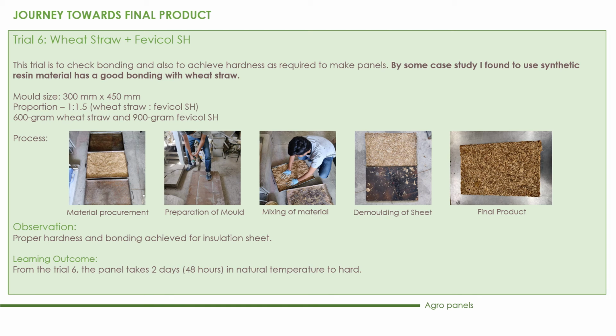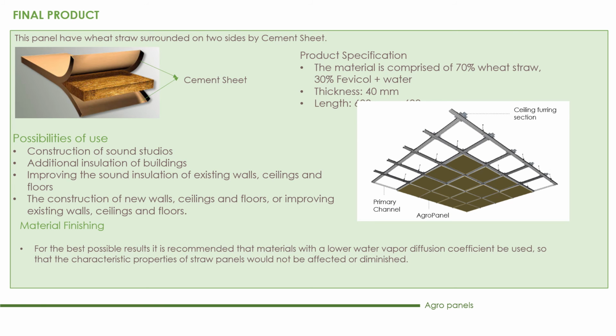Now for the final trial, after doing some literature study, I found that synthetic resin material has good bonding nature with wheat straw. After the panel was cast and left to harden over a period of 48 hours, proper hardness and bonding was observed. For finalizing the product, an 8 mm thick cement sheet was used to make a composite panel by covering the agro panel from both sides so as to provide better insulation and protection against wear and tear.